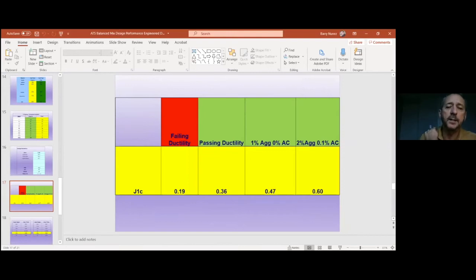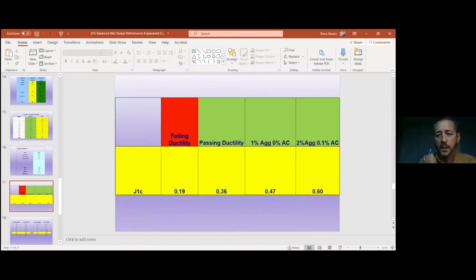So Louisiana has a ductility spec and some states have dropped it. But I think this proves a real need for it in your liquid asphalts. We happen to have some liquid asphalt that did not pass Louisiana's ductility spec. And after talking to Dr. Luwe and Sam, we said, you know what, let's make a set of SCBs on that, just with the original design, and compare that. Well, you can see it's extremely low, a 0.19. Our first passing was a 0.36. And then when we made the first 1% change, we got to 0.47.